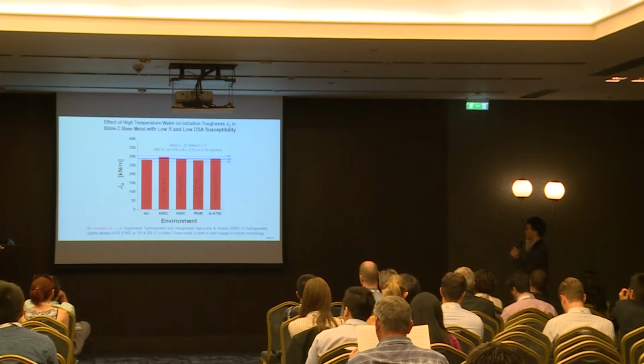So here is the result of the reference material, which has a low sulfur content and also low DSA. As you can see here, exposure to different high temperature water environments did not reveal any degradation compared to the test conducted in air. And all of the crack initiation resistance was within the scatter band. So for this reference steel with low sulfur content and low DSA, there's no high temperature water effect.